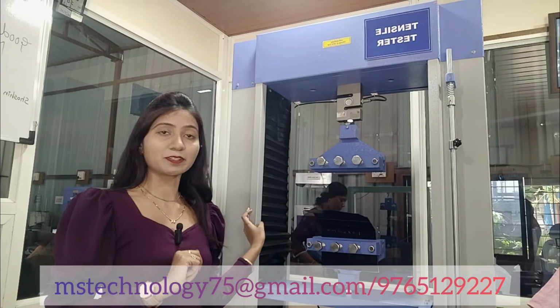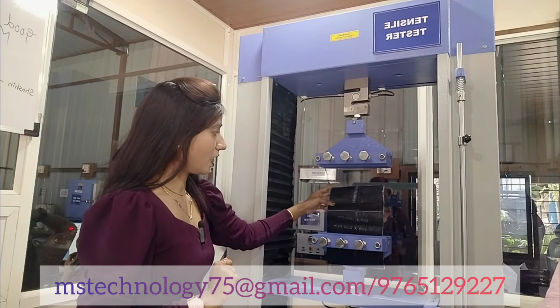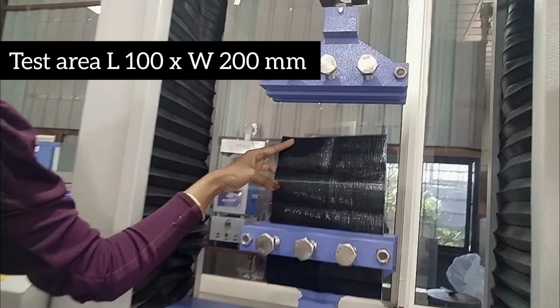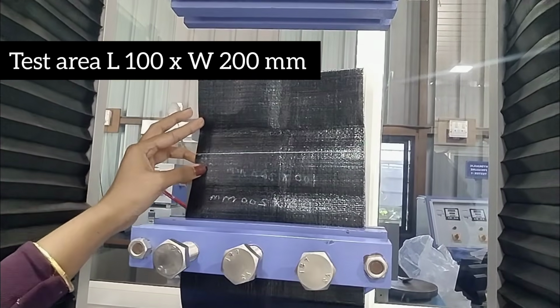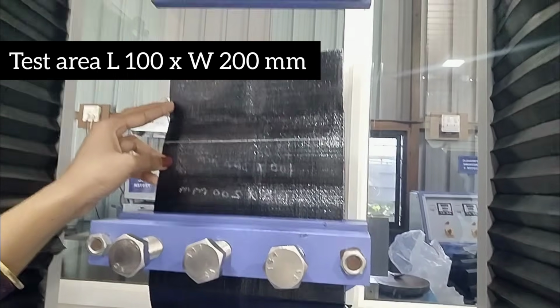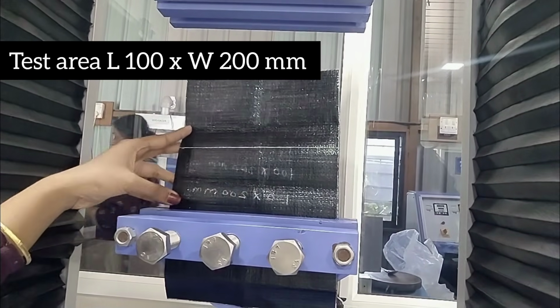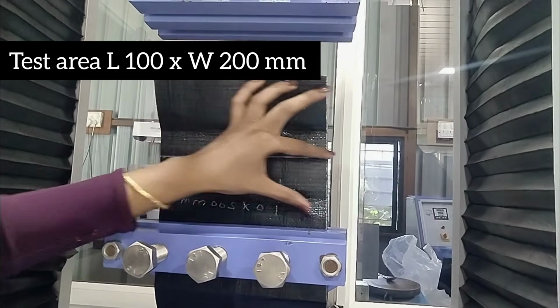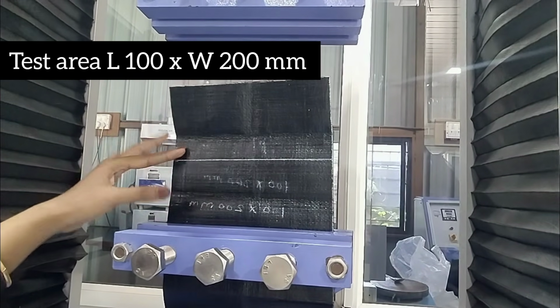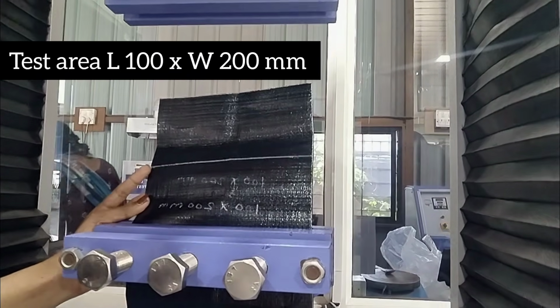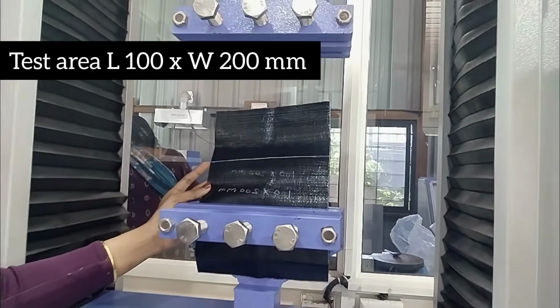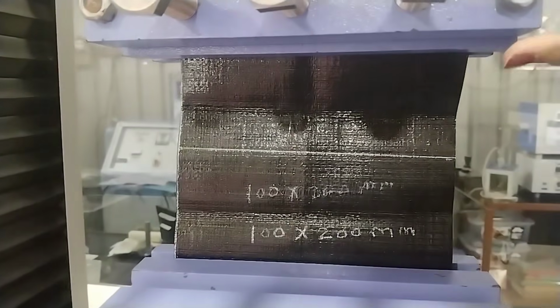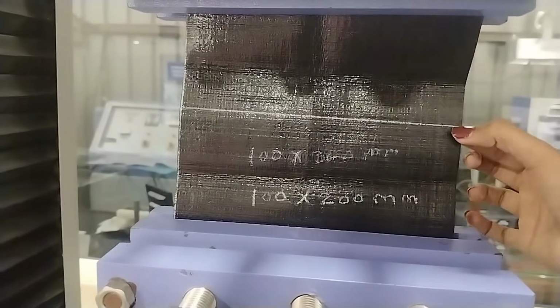Now, let's see the procedure. Here, I have taken a sample of geomembrane. For testing, we required a sample size that is 100 by 200 mm. 200 is the width and 100 is the gauge length. Here I have made marking on this sample and had placed it in tensile jaw. One end of the sample we already had fixed in this lower jaw. Now we have to take this upper jaw at this level and we have to fix it.